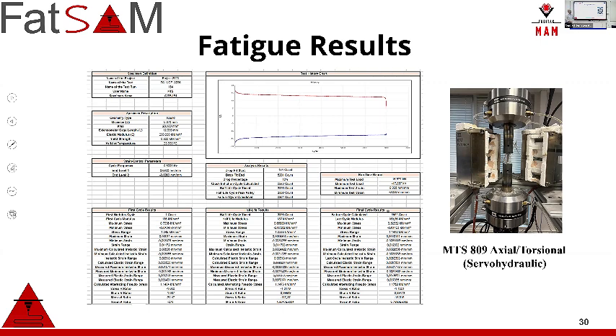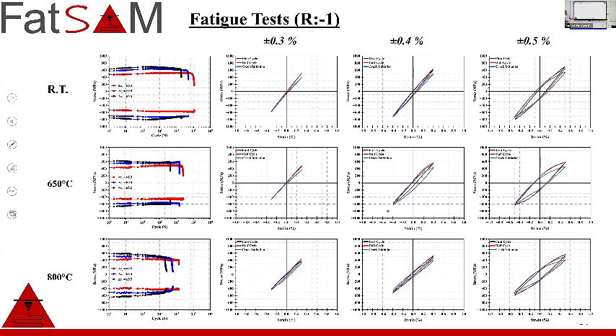For each hysteresis, the advantages of strain control tests and extensometers are these. Just tell me the cycle you want to see, and I can show the hysteresis loop or strain amplitude and stress amplitude with displacement ratio or strain ratio. This is the biggest advantage of using extensometers and thermocouples.